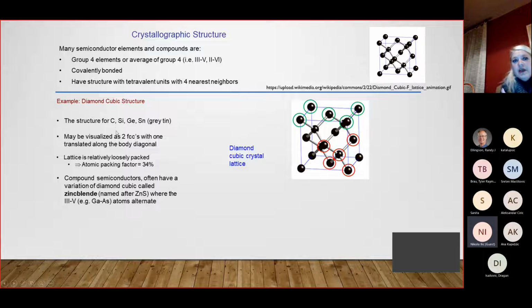This structure is found in carbon, silicon, germanium, and a modification of tin which we call gray tin. Here we see that every atom, for instance this one, has 4 nearest neighbors, as described here. Here you can see the 4 connections. This structure may also be visualized as 2 FCC lattices with 1 translated along the body diagonal. That means you have an atom at every corner of this cell, and you also have 1 in the middle, which lies along the diagonal of this side of the crystal lattice.